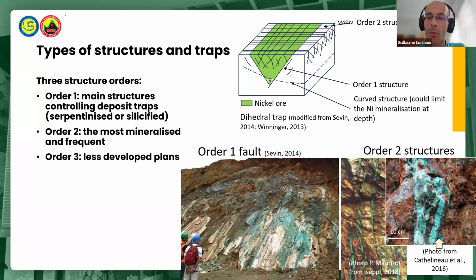This order 1 structure controls water flow enriched in leached nickel, which precipitates mainly in order 2 structures, which are more frequent and less open, and which tend to slow down free circulation and contribute to nickel precipitation. Order 2 structures correspond to the matrix of the trap and are the most mineralized structures. Well, this is an example, obviously, of garnierite-rich veins, which constitute, in that case, the matrix of the trap. The different types of traps for nickel mineralization are dihedral traps, curved structures, like this one here, and dolines, intersection of structures.